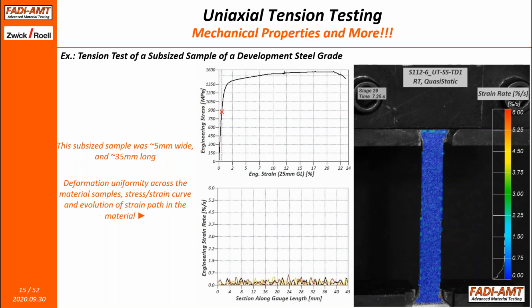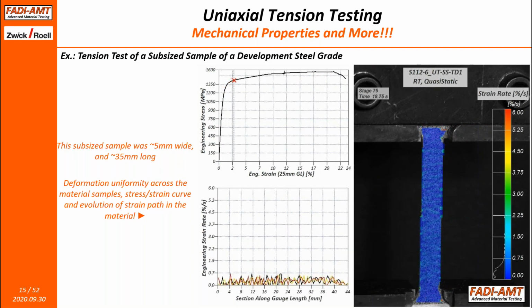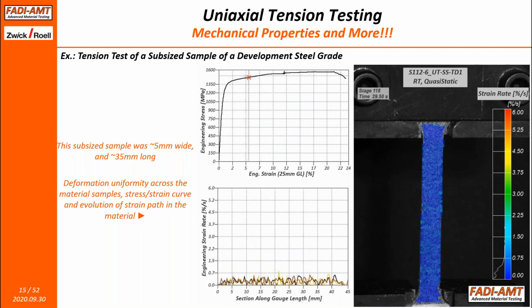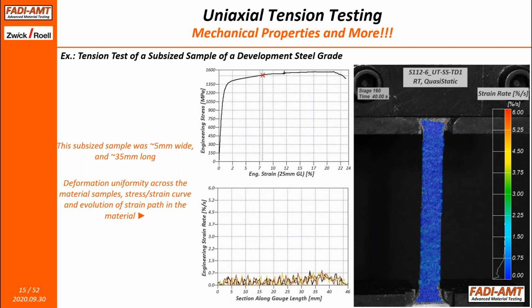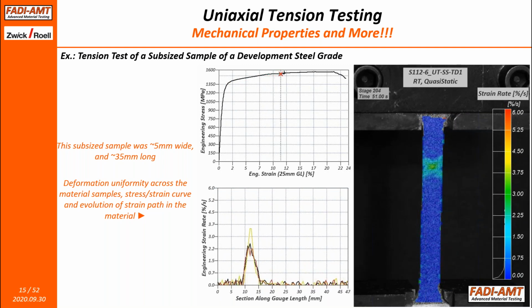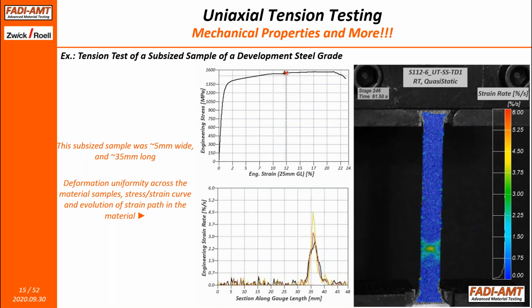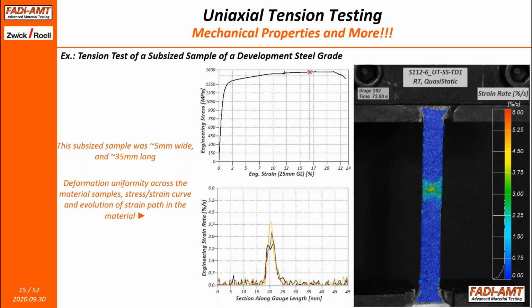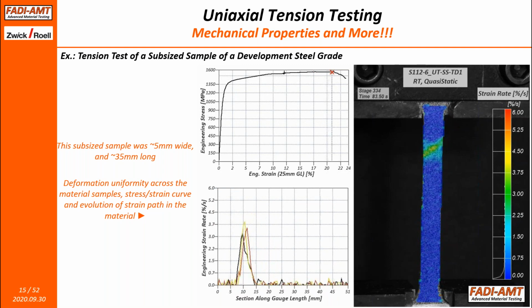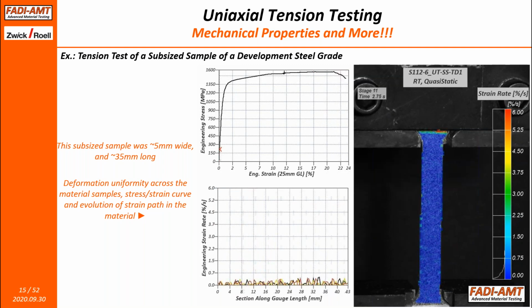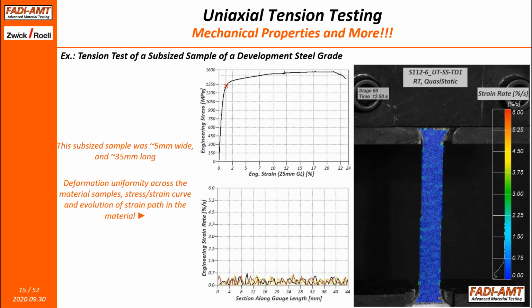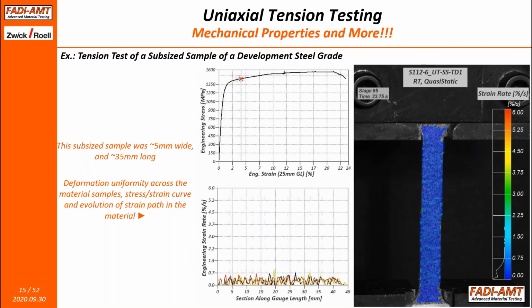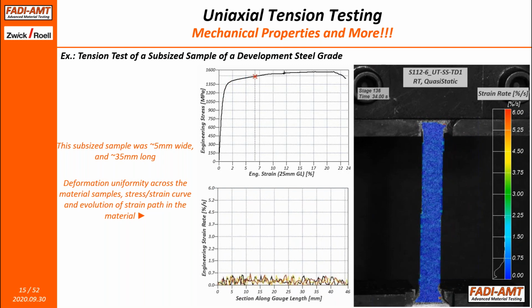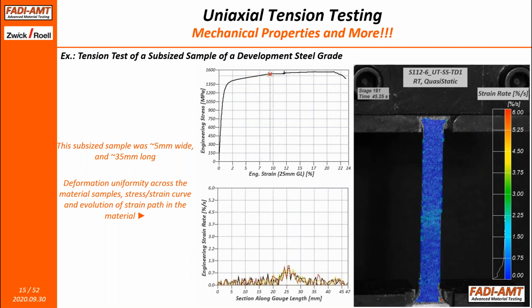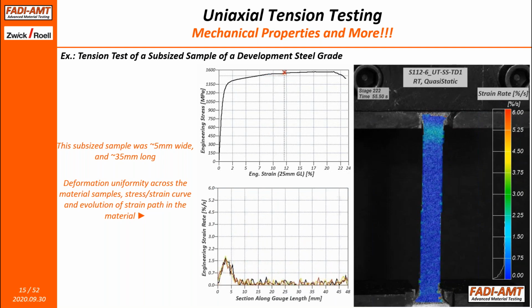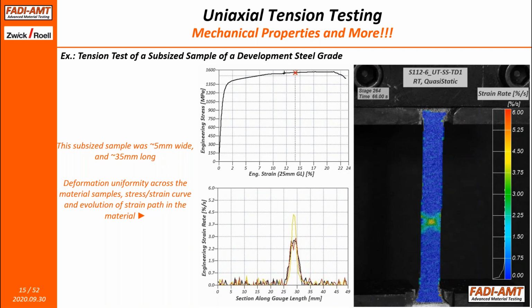But let's go to those cases where we have to go smaller and larger. This is a subsized sample. This is from a material development effort for a steel grade. And with the limited material supply, we had to go with smaller samples. But more importantly here, this was a special development material, and we wanted to study the exact behavior of the material. And that's where DIC offers something that cannot be offered by conventional extensometry, which is how the material is deforming. Is it uniform? Is it not uniform? And in this particular case, you can obviously see that the material is having a banding response that is important to identify, which cannot be identified without DIC.